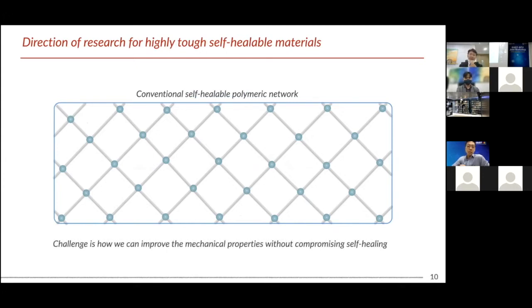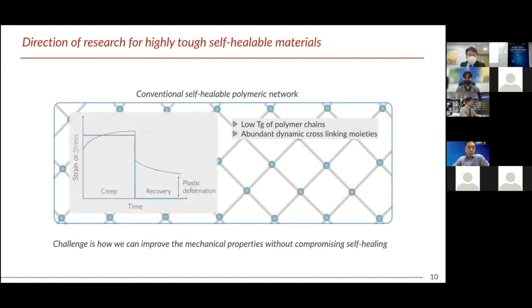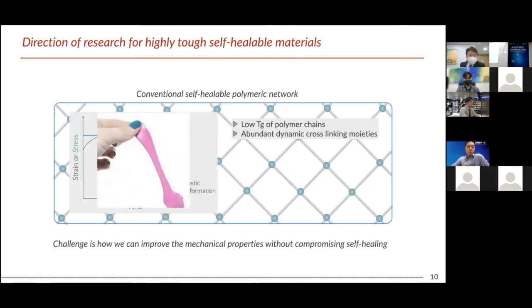However, the difficulty is the poor mechanical properties of self-healing materials, because they are based on a very low Tg polymer chain and are solely based on dynamic bonds. They conventionally show significant creep and plastic deformation under high strain. Simply speaking, they have more gum-like properties rather than those of a fully elastic elastomer. So we need to overcome these mechanical limitations in order to apply them to stretchable or soft electronics.